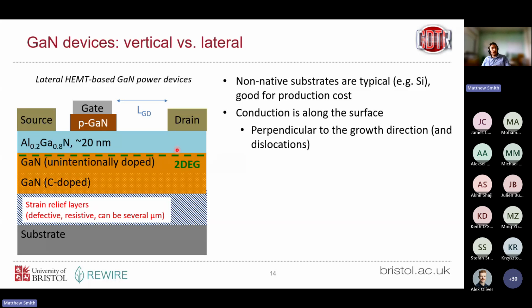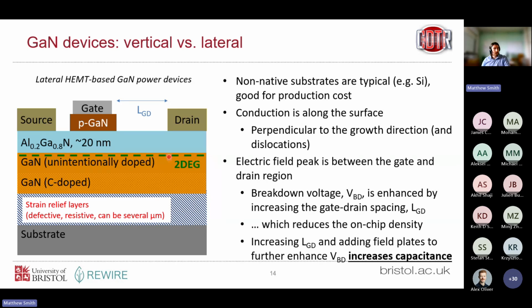So they tend not to have too much of an impact on device performance. They do have a bit of an impact, but we can get away with a relatively high dislocation density because our 2-DEG is perpendicular to them.